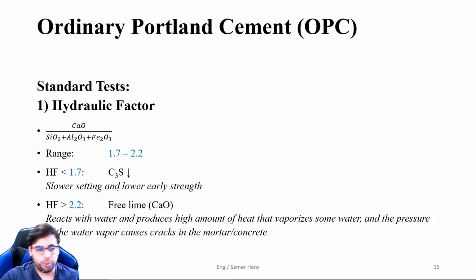All right. So what happens if it exceeds the maximum? Then we have free lime in the cement. Free lime, as in the calcium oxide already reacted with all the available other oxides, and there is some more calcium oxide that didn't find any oxides to react with. And why is this a problem for us? This calcium oxide is the quicklime, if you know quicklime from studying chemistry before. This reacts with water and produces a high amount of heat. So this is a highly exothermic reaction which produces heat.